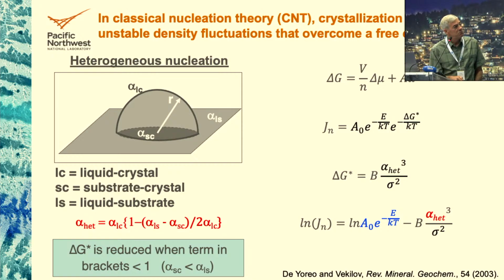All right, so the rate equation looks identical to what it was before. The form of the free energy barrier is the same as it was before. If we take the log of this expression, we now find that the log of the rate is proportional to 1 over the supersaturation squared. The slope gives us this interfacial free energy. It's this composite term, but that's okay. And the intercept gives us this prefactor, which tells us about the kinetics of ion binding and desolvation, okay?